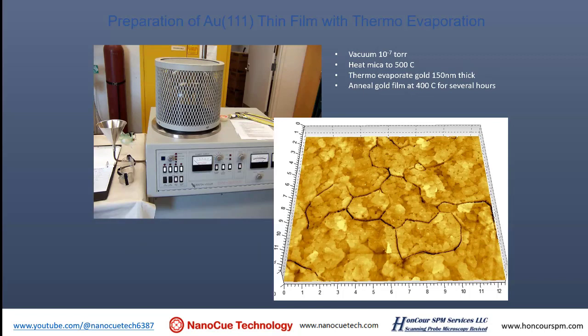And then at a certain temperature, the gold will boil. They literally boil. You can see that it actually rotates. And then after that, the gold becomes vapor. The vapor will be deposited on the surface of mica and form droplets. And then at 400 degrees C, you anneal for several hours. These droplets form a flat surface. The one on the right is the gold surface.